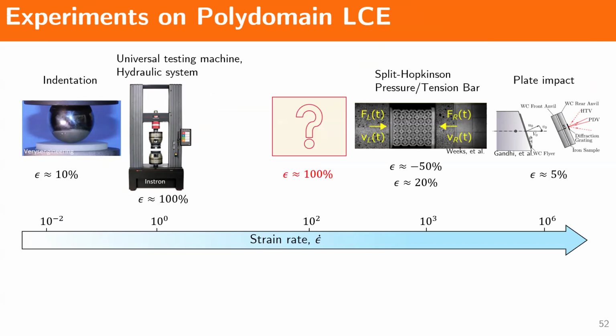When we actually started looking into the high strain rate behavior of this liquid crystal, it was hard, because the high strain rate behavior is not very well characterized for these materials. I think the reason is that there does not exist an established experimental setup for these soft material systems that can probe the behavior under the deformation regime we're interested in. In particular, we're interested in the regime of high strain rate and also pretty large strain.